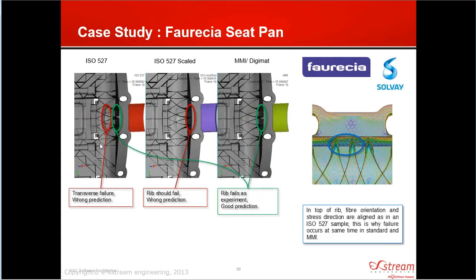As we move further along in the analysis, in the first case, that initial failure that shouldn't have happened has continued to progress and has moved transversely along the part. We have started to see the rib failure, or the rib buckling, that we expected to see, so that's very positive for this first isotropic approach, but we do have this other failure that we didn't mean to happen. In the second approach, we have not had the failure that we should expect to see on this softer isotropic model. And in the third approach with Digimat, we have captured that failure.